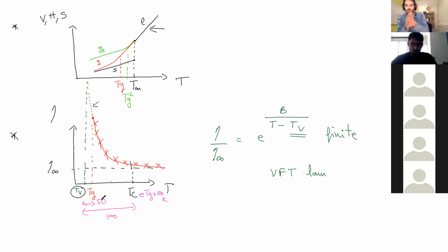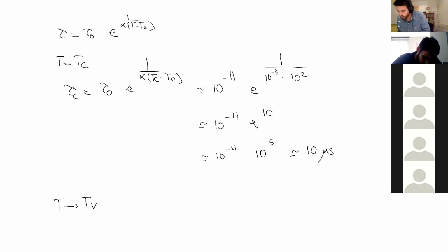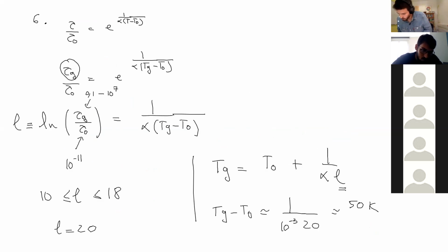Basically, you would have a hypothetical divergence. 50 degrees above that, you have the moment where you cannot see anything, which is typically Tg. And 50 degrees above that, you reach a standard liquid. Okay, so everything is going on in a very narrow temperature region. And the free volume picture allows us to get the good orders of magnitude, although it has plenty of problems otherwise. We will discuss that later. Okay, actually we will discuss that now.